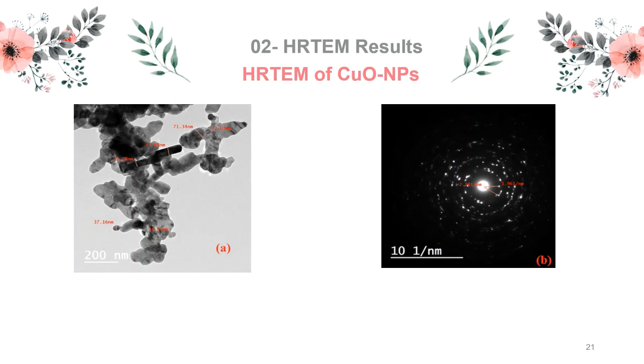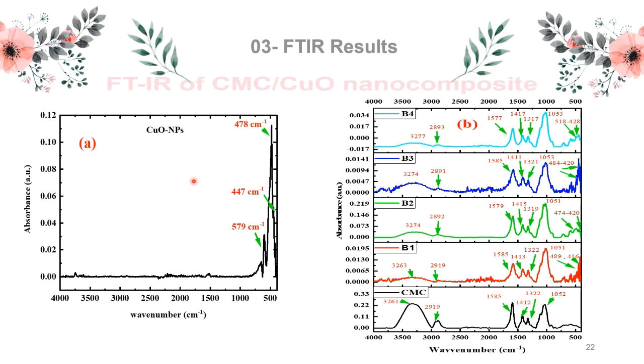This figure presents the FTIR absorption spectra of copper oxide nanoparticles, which contains only 3 absorption bands that can be attributed to the copper oxide stretching vibration. Additionally, no other IR active mode was seen in this region, ruling out the possibility of another phase. However, this figure presents the FTIR spectra of pure CMC and CMC containing different concentrations of copper oxide nanoparticles. The key feature bands of CMC are revealed in the FTIR spectrum of all samples.